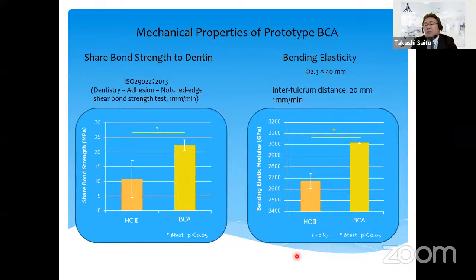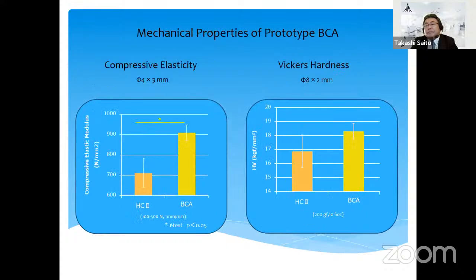Next, we checked the mechanical properties of prototype BCA regarding shear bond strength to dentin and bending elasticity. Both values for BCA are significantly higher than Hybrid Coat 2. It is speculated that in the case of the prototype BCA, calcium dissociation from the CMET monomer causes another binding with calcium of dentin apatite and also with calcium of another CMET monomer. So CMET may function as a cross-linker to dentin and other monomers, and as the source of calcium ions for mineral induction also. Regarding the compressive elasticity and Vickers hardness, both values for the prototype BCA are also higher than Hybrid Coat 2.